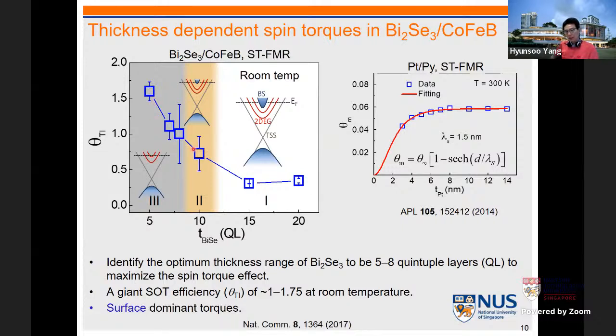This is a big contrast if you look at the conventional platinum material as a function of thickness. Typically they increase and then saturate. So this can be understood by the conventional spin Hall physics, and we typically attribute it to the bulk band dominating. But on the other hand, if you look at this bismuth selenide, the thickness trend is exactly opposite, which indicates it is a surface-dominant transport.